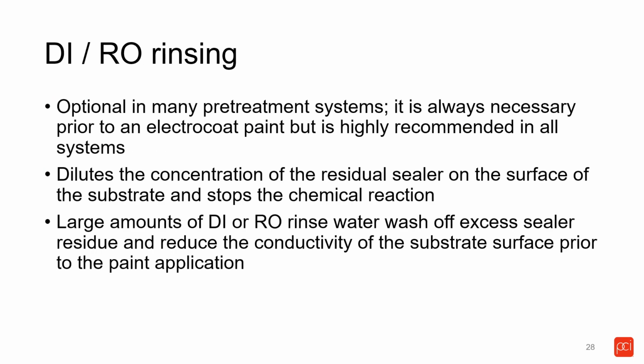For your final stage, even though with powder you don't necessarily need a DI or RO rinse, we highly recommend it because it's the cleanest water you can have, and it will give you the cleanest surface, free of inorganic salts, before you move on to your paint system for the best paint adhesion you can get. The inorganic salts can interfere with paint adhesion, so the DI or RO rinse is the best rinse you can have.